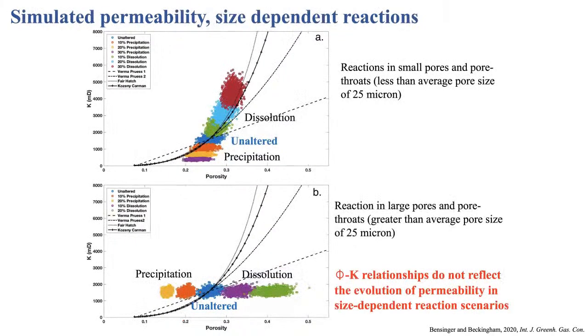Now, if we look at some of the size-dependent reactions, on the top here, if the reactions only occur in small pores and pore throats, you can see we get much more extensive changes in permeability with dissolution and precipitation, and that this is not captured as well with these macroscopic equations. If the reactions occur only in large pores and pore throats on the bottom, you have large increases or decreases in porosity with really little change in permeability, and this is also not reflected well by the porosity permeability equations.